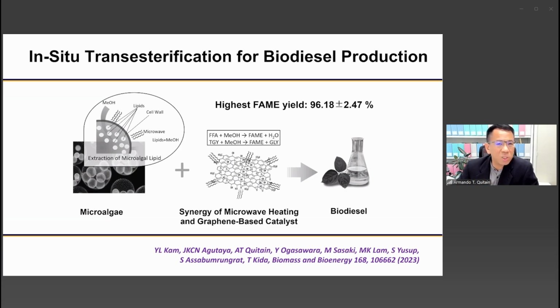And here we applied in situ transesterification. When we say in situ transesterification, we did not extract the oil present in microalgae. We just added the solvent, which also serves as the reactant for the transesterification, methanol. Methanol is capable of extracting the oil present in microalgae. And here, we also apply microwave and graphene oxide as catalysts. And as a result, we get the highest yield of biodiesel, which is the fatty acid methyl ester, of about 96%.